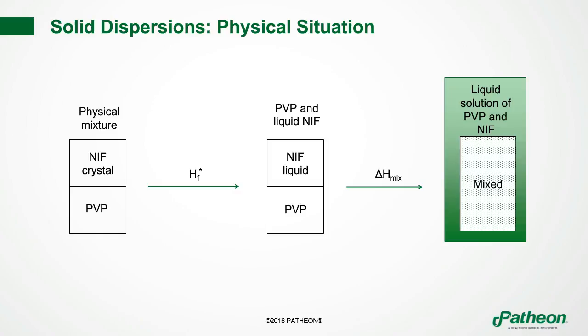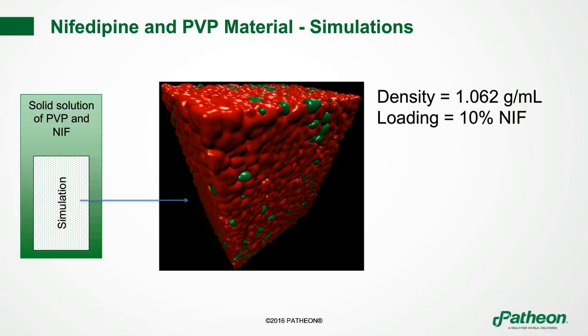Here on this slide, what you see is nifedipine and PVP after a simulation has been run. Again, I'm taking that solid solution of PVP and nifedipine where I've taken the crystal, melted it, and then added that to the PVP, and I form this intimate mixture, this dispersion. Well, let's simulate that by placing lots of different polymer molecules and drug molecules together and letting the molecular dynamics simulation run to intimately mix them. And what you see in the middle is the result of that. So this is a 10% by weight loaded dispersion of nifedipine and PVP.